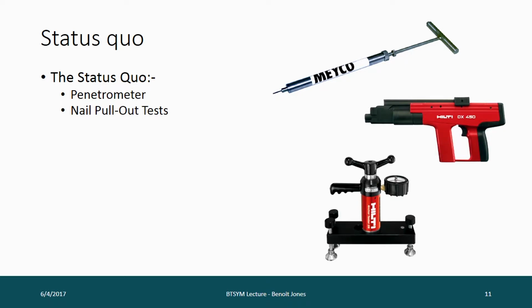So there's a variety of problems with these tests. One is that they're very local. You're only testing really small volumes of shotcrete, and the heterogeneity of the shotcrete itself is quite important. For instance, with the penetrometer, if you hit a largish bit of aggregate early on in pushing it in, it will obviously have an effect.